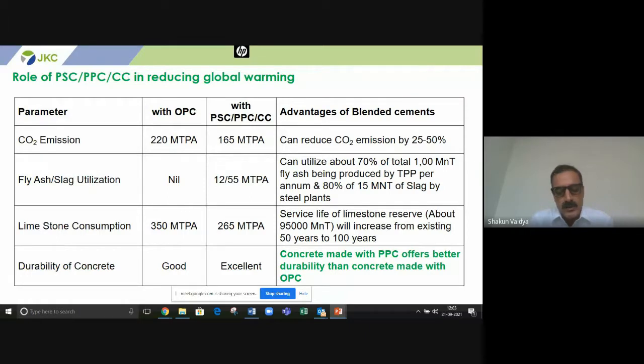So by producing blended cements, how are we reducing global warming? CO2 emission can be brought down 25 to 50%. Fly ash utilization of 60-70% can be effectively achieved. And we can enhance the life of limestone reserves, which at present is 50 to 100 years, if we opt to go for blended cements, where we require less clinker. Less clinker means less burning of limestone. Less burning of limestone means less burning of coal, and even lesser emission of carbon dioxide into the air.